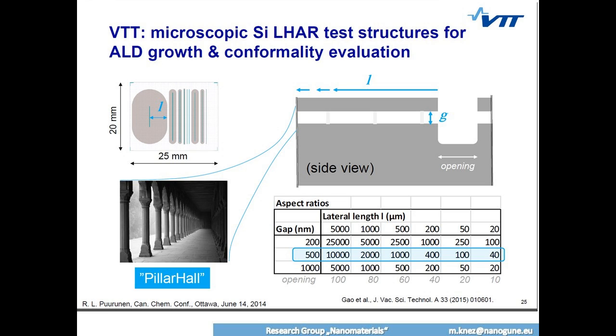And once they deposit inside of this channel, they will be either consumed or they will be limited by your process parameters. In either way, you will have a gradient here for your deposition. And once you remove this roof after the process, you can just see with your bare eye the color change along this line. They can produce those kind of chips with various sizes, and they did those experiments.